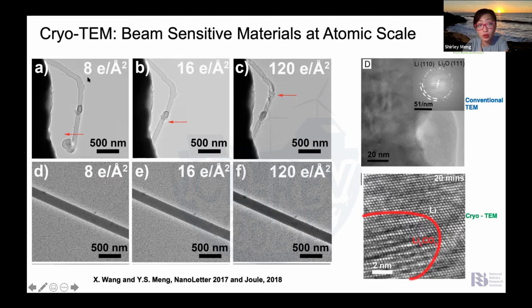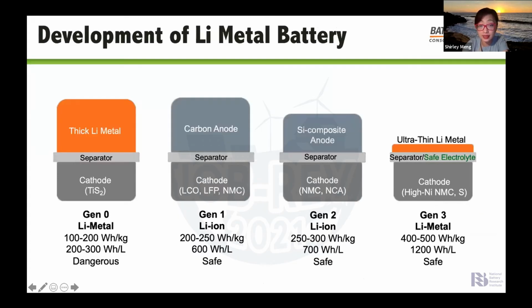So when you do the imaging, even if the top panel is room temperature, even if you do nothing, you can see the whisker is changing. And this change is not coming from the materials itself, it's actually coming from the interaction between the beam and the matter. Now with the cryogenic method, we can now stabilize the image, and you can see the beautiful lattices of the lithium metal and its SEI.